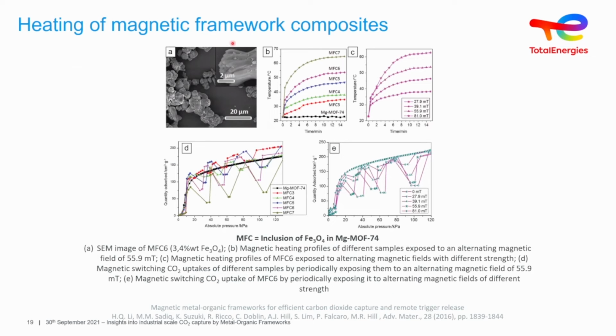Think of magnetic frameworks as well, and I think this is something of interest. Again, this is from Matthew Hill's group. And what they did is they took a quite large pore MOF, this MOF 74, and they put in iron oxide. So the iron oxide inside the pores, this magnetite, interacts with a magnetic field, and we can get magnetic heating. Again, of interest because a magnetic field is a source of energy which is from electricity, which could in the future be renewables, for example, and uses much less energy than we would use using a conventional steam, for example. So a nice, interesting way forward in terms of an interesting result.